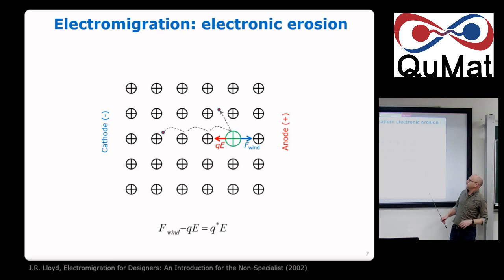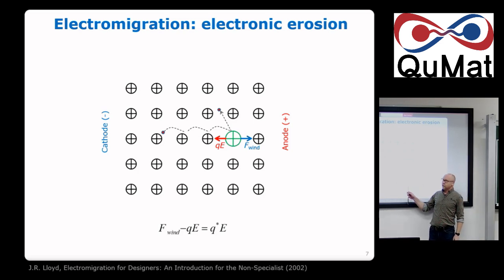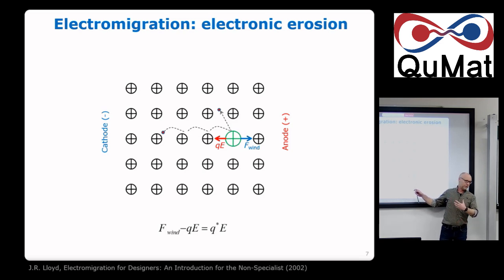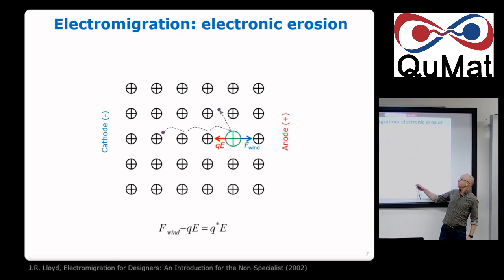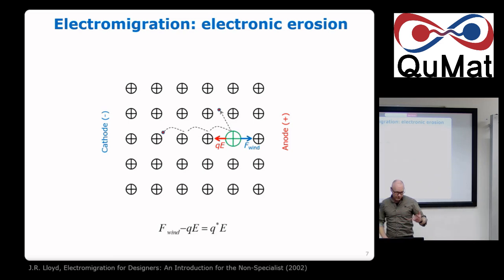Once you look at the classical picture, when you apply an electric field in that direction, you have an ion here, which is positive, a foreign atom that's well bigger, and therefore you have a direct force. But the force produced by the electrons is also proportional to the electric field, because the more electric field you have, the more electrons you have, and therefore the total force is proportional to the electric field. There is still a huge discussion about how much of the force comes from this side and how much from the other side, and even whether they are additive or not, because it's not a simple calculation. Many people thought that this force is zero because it's completely screened.